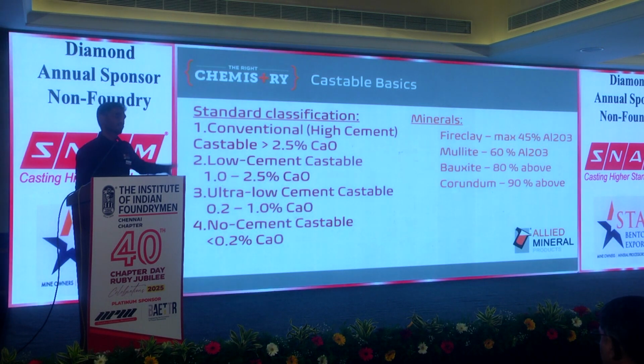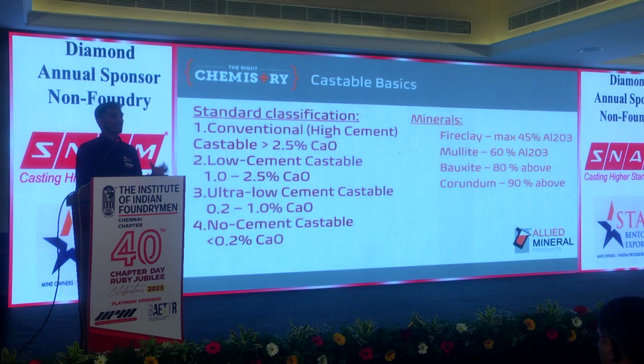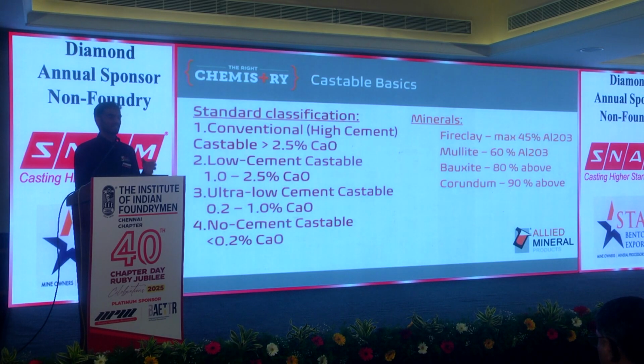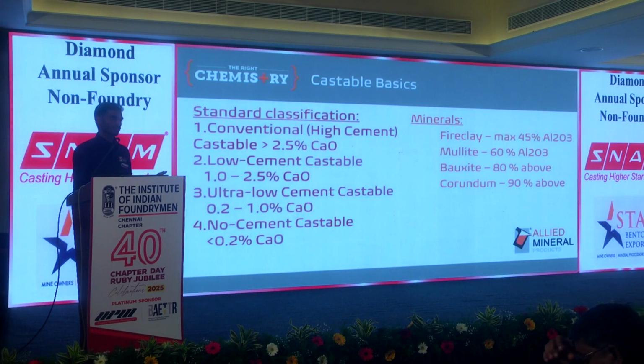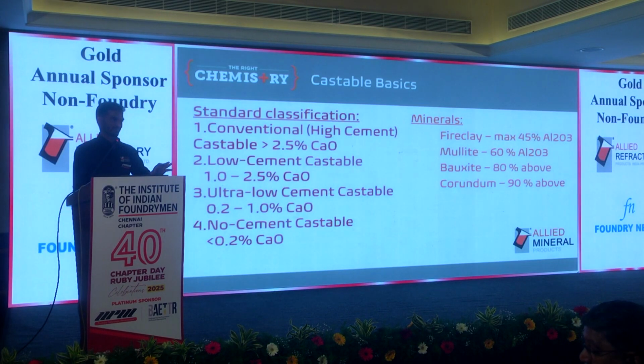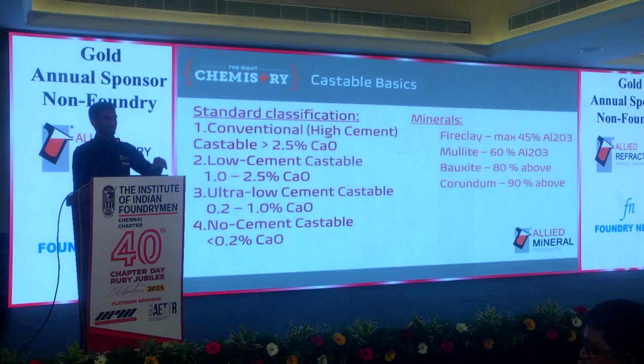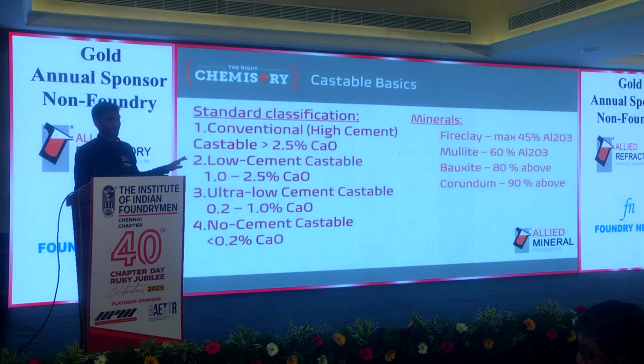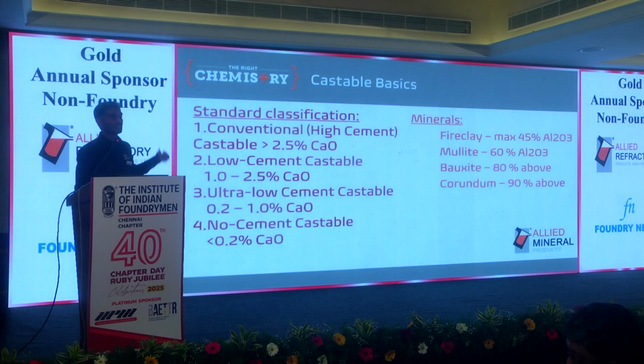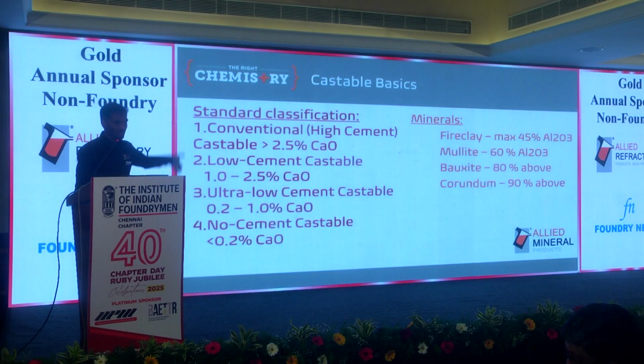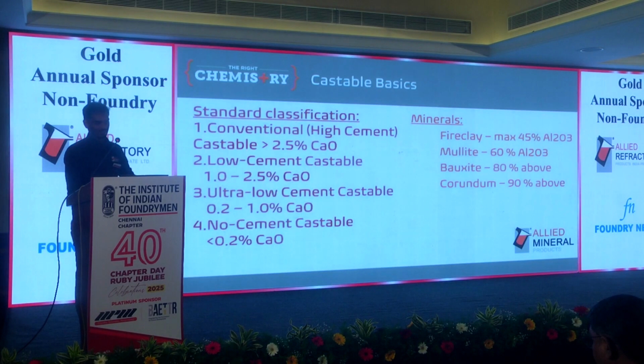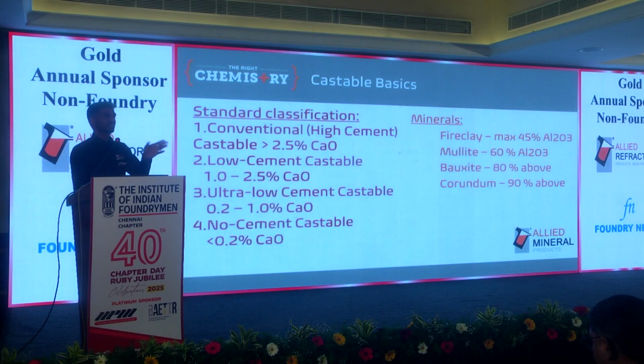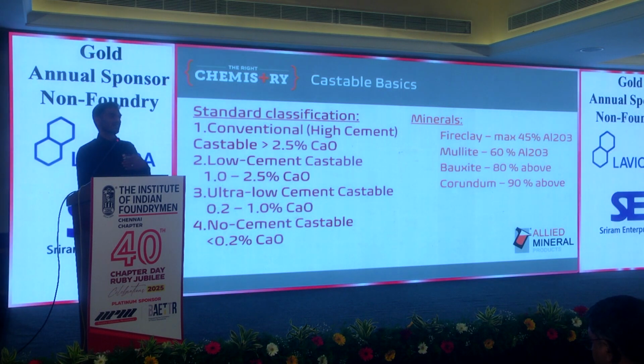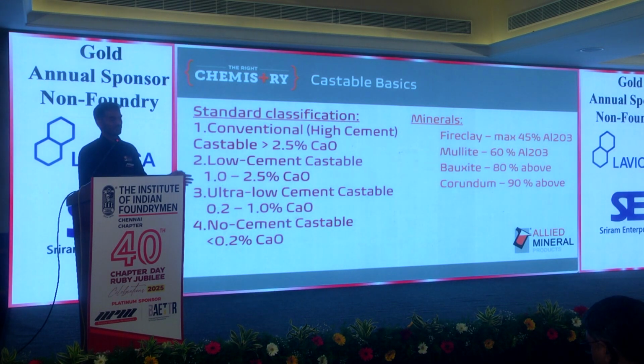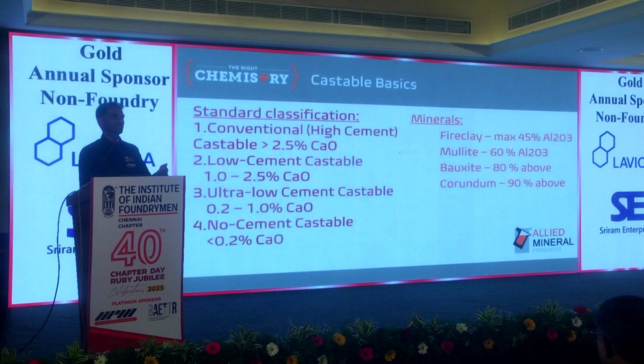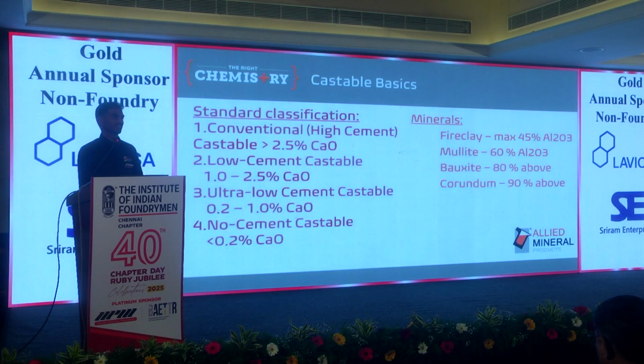But that's a challenge with no cement castables because the green strength is way low. So you have to be very careful and precise whenever you pull the form out, until you introduce the heat into the system. If the heating is done, then it gets the strength. But the green strength is very low. With conventional cement, the green strength is higher compared to the other cements, which are low in 2, 3 and 4. So that makes the difference. Why people are moving from conventional to low cement, ultra low cement, or no cement is because of that: to have high performance and less non-wetting properties, those things.